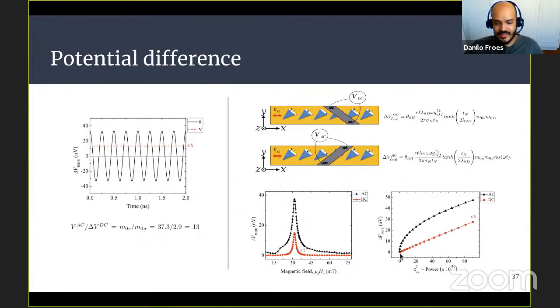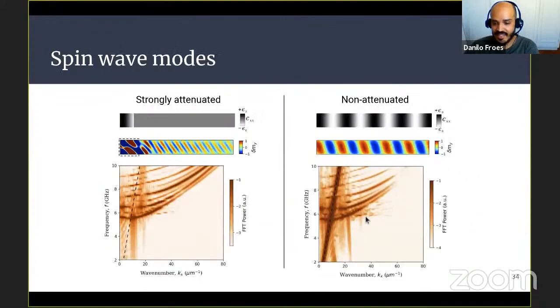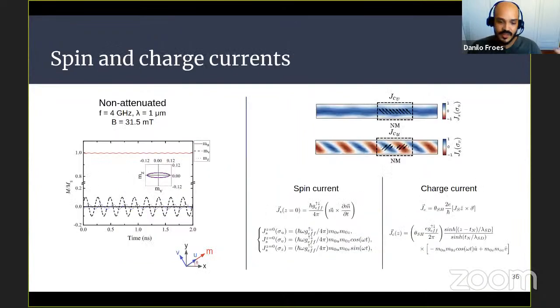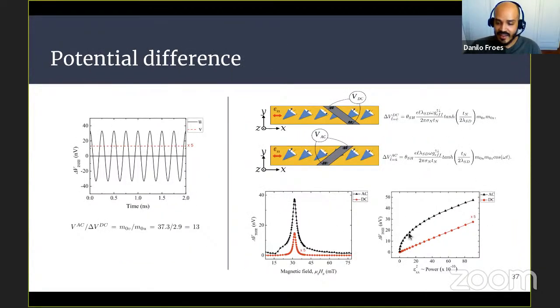Also, if you change the magnetic field, this is a resonant phenomenon. When the acoustic wave and the magnetic wave natural dispersion cross each other and match, we have this maximum in ISHE voltage. So this can be a measurement of where the two curves cross. And here we are in a frequency range where the anti-crossing we would expect is much higher. We are not in the frequency range of that anti-crossing of curves due to the magnetoelastic effect. It's important to highlight this. And here is how the ISHE voltage varies with the power. The AC has this square root behavior and the DC has this linear behavior.